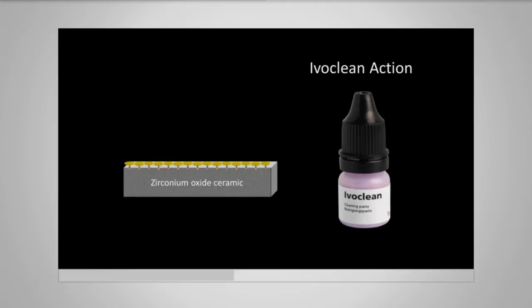Now, to make matters worse, sometimes people would clean the inside of zirconia restoration with phosphoric acid cement. And that was terrible because then the phosphoric acid cement took up all of the sites that remained, and the phosphate groups in the phosphoric acid cement took up all the remaining sites, and you couldn't bond anything to it.